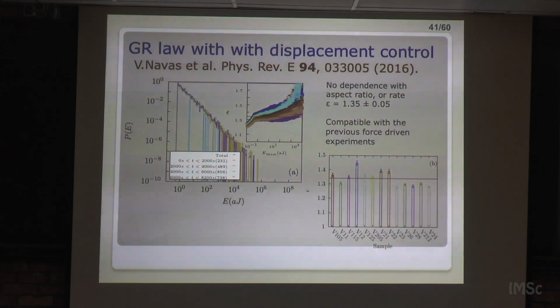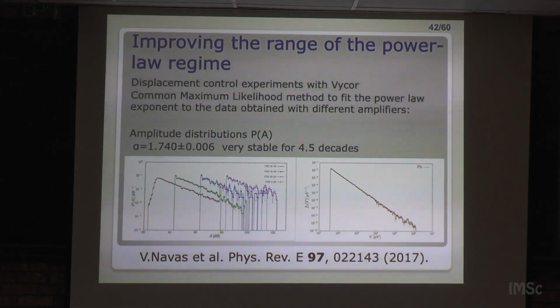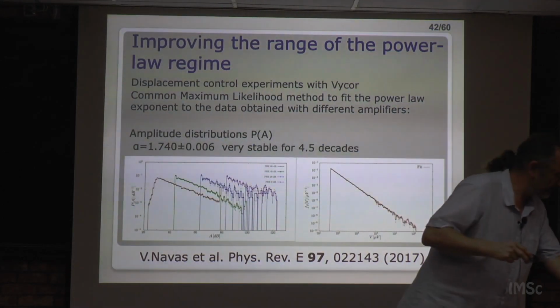This variation, we are not sure whether it's just sample-to-sample or there is really a smaller exponent when you have displacement control. But apparently, at least, it's a very tiny difference. It could also be related to the fact that the overlap of the avalanches is not equivalent when you have force control than when you have displacement control. Okay, and that's just, yeah, now I am getting out of the time, I think, but let me check.